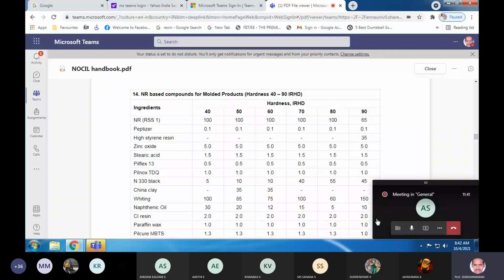And in case of V-belt, conveyor belt, they all undergo some cyclic load. Under cyclic loading, certain parts of the product surface are specifically exposed to atmospheric oxygen or ozone. And what is the quantity that is added here? Just about 0.5. All right.